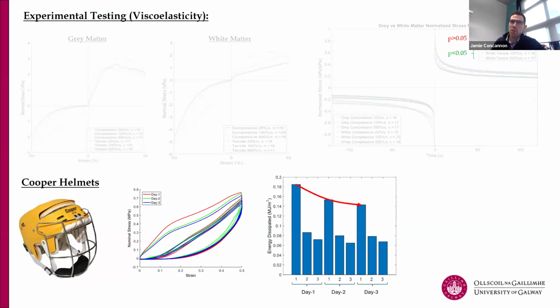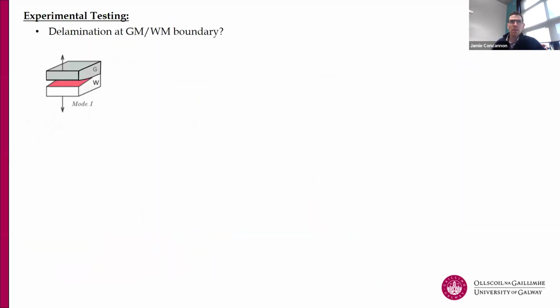So that was basically the first thing. And then we said, okay, we'll look at what happened in day 2, and this recovery happens. So once you leave it for that 24 hours, you regain that energy dissipation again, and then it decays, and then you regain it again. Now, not all the way to 100%, but our take-home message from this is that the worst thing that can happen is you get these repeated injuries in such a short time frame, so that the energy dissipation is minimal.